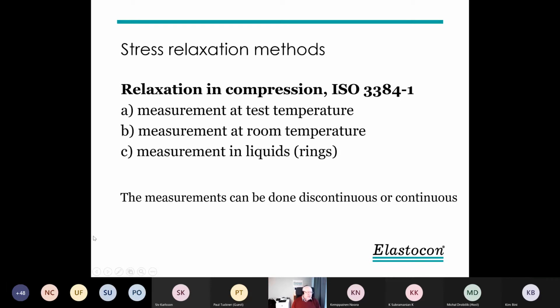In our main standard, ISO 3384 Part 1, it's called nowadays because we added a Part 2 some years ago. We have, in fact, two ways of doing it. Method A is a measurement at test temperature. It means that we measure the counter force at the test temperature, and we do all the measurement at test temperature. In method B, the measurement of the force is done at laboratory room temperature, normally 23 Celsius.